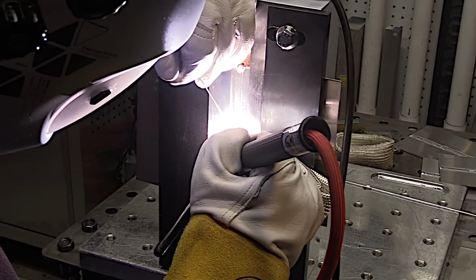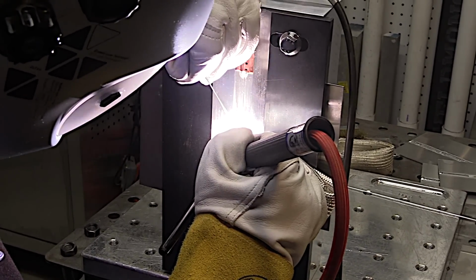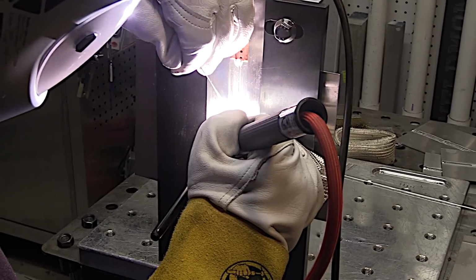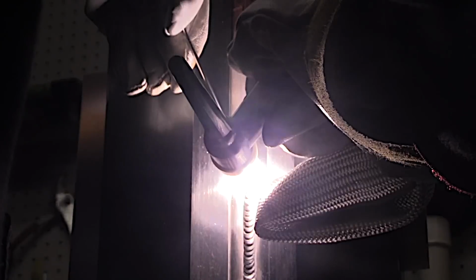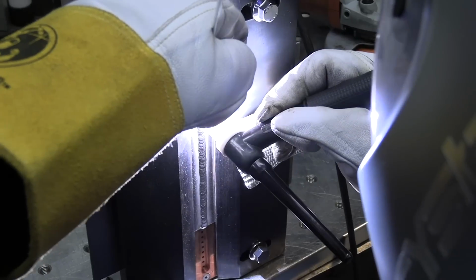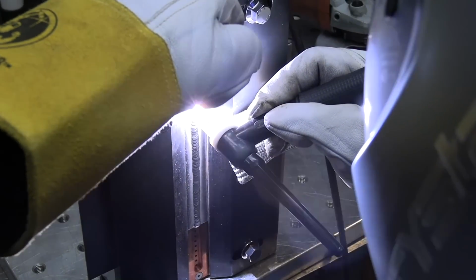So every time you dab rod on a test like this, you need to just wait for half a second or so and let things smooth out and outgas. When you're welding in the 3G or vertical up position like this, your travel speed automatically slows down. What you have to remember is each ripple in that bead is a freeze line. That means when you add filler metal, it chills the puddle a little bit. So waiting around for just a half a second or less, letting things normalize, letting things outgas if they want to, can help you prevent porosity on a test weld.